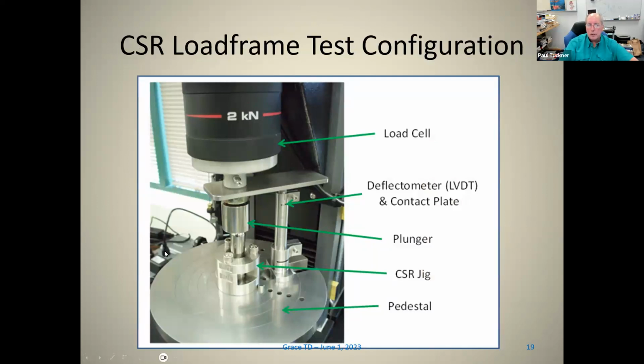So this is the load deflection. This is the CSR test configuration that I use in my lab. On top, you see the load cell, and below that, you see a contact plate for a deflectometer. So you can have a deflectometer here, and that allows you to measure the actual deflection that's occurring and takes out the deflection that occurs in the load cell, which helps you obtain a higher stiffness ratio, which I'll talk about in a little bit.